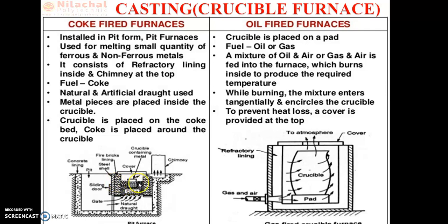After the coke bed is completely ignited, with the help of a strainer we move the coke to the side, preparing a space so that the crucible is put inside here. Thereafter, using a rod, we put the whole burnt coke around the crucible. The crucible is surrounded from all sides with coke, and its top is covered. Here we have a cover that prevents the escape of gases.